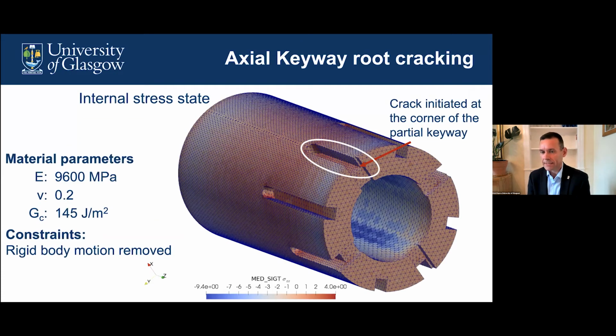Here's a graphite brick. You can see it's a complicated geometry. We've removed rigid body motion. We've seeded a crack. We've got a crack initiation at the corner of the so-called keyway root. And that's where we think that the crack is most likely to be initiated. So we always initiate the crack. Okay, so there's no crack initiation component in this. We initiate a crack, and then we run the analysis.